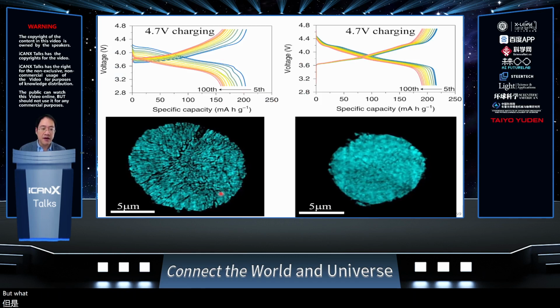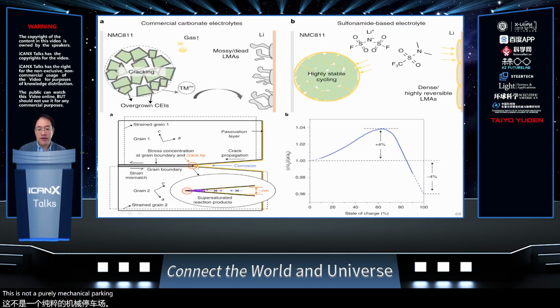But what we have found was that this is not a purely mechanical cracking problem, because all we have done is switch, we keep the same electrode, the same loading, the same charging rate and discharging policy, just by changing to this sulfonamide-based electrolyte. This is done by Dr.